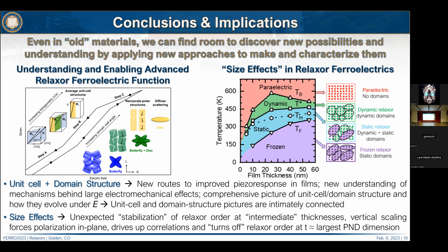Yep. Yeah, that's a great question, by the way. So the way these experiments work is we don't get them in one shot. We're doing these things typically in the kilohertz frequency ranges, and we often have to do many, many cycles at each field to get sufficient data, and then we average those. So even within that data that I showed you, it's millions of cycles. We've also done fatigue-based experiments on these sorts of things. Is there a big change? Do they start to coarsen and never come back? We have not seen that in the low strain state films.